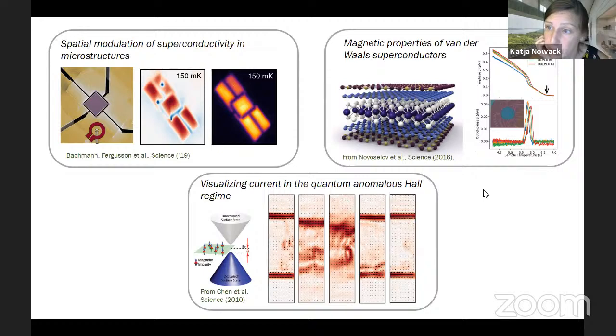So with the squids that I'm currently using, we could make the pickup loop that you saw smaller. But actually, in the case of the squids that we are using, that wouldn't help much because there are two factors that influence your spatial resolution: the size of your sensitive area, and the height at which you scan. And it turns out, because we have this field coil on chip and some other additional circuitry that I actually didn't talk about that allows us to fully linearize the flux response,